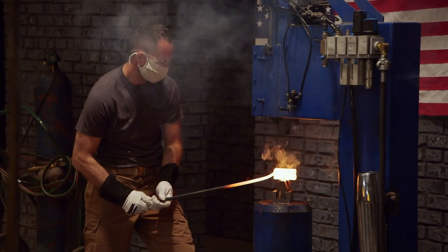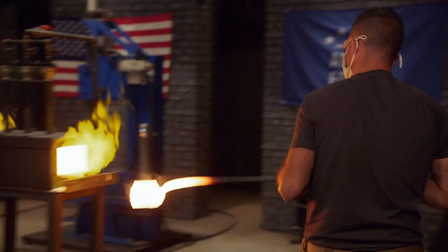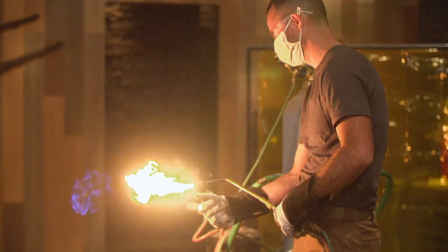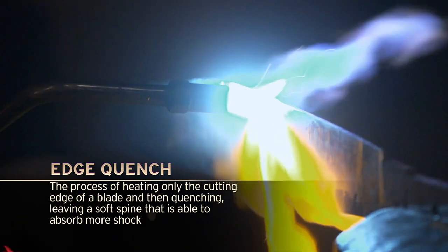I get my weld set in the press, and then I move over to Big Blue. My plan is to draw those out and then cut them into threes, so that's going to be 39 layers in each billet. I bring it over the press and give it a little bit of lovin' — it's consolidating those welds in the over 200 layers of steel. I've got my billet into a blade shape and I'm trying to get to a quench, so my plan right now is just to do the edge quench. By edge quenching, I ensure that the edge is hard without causing a warp.